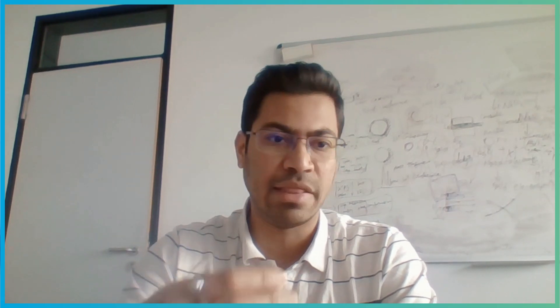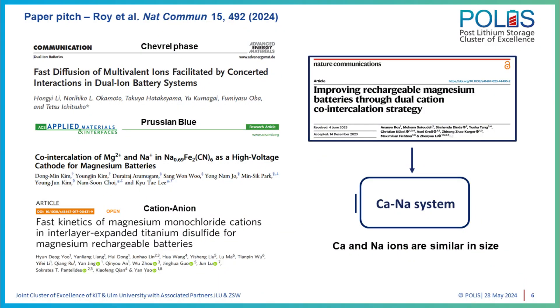My work was focusing on layered materials, but there have been reports previously — especially with the well-known Chevrel phase — where they talked about magnesium-lithium co-intercalation, which improved the overpotential issues that magnesium batteries normally face. However, in that paper, the effect or phenomena was very different to what we found in layered materials, because the Chevrel phase is a different structure.